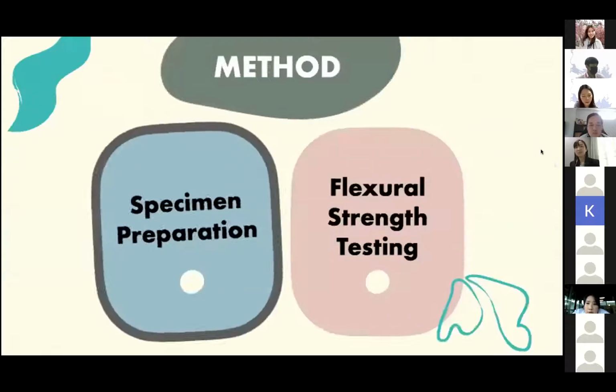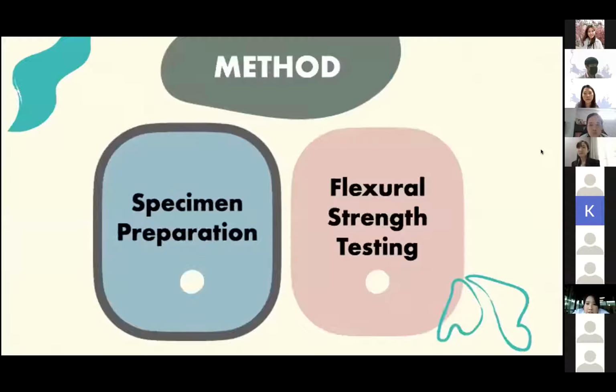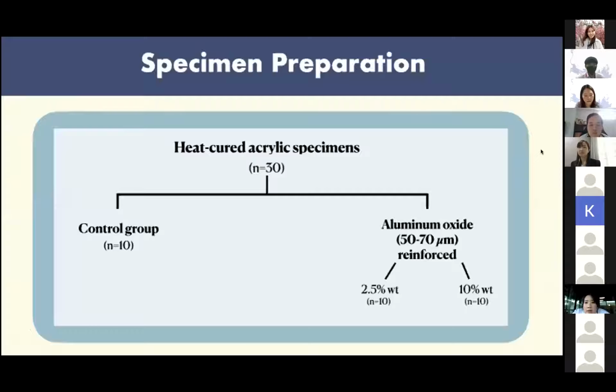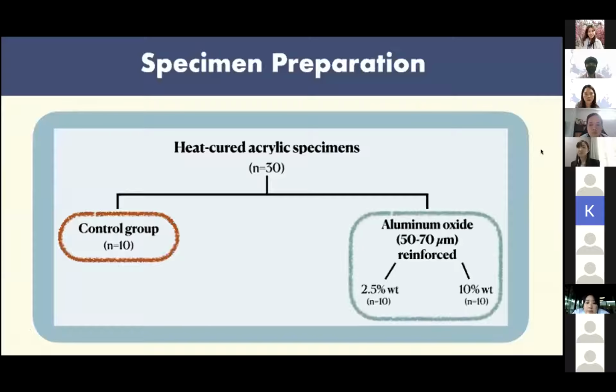Materials and methods. The materials used are as shown. Starting with the specimen preparation. 30 heat-cured acrylic specimens were fabricated. All specimens were divided into 3 groups. 10 specimens were the control group, which was intact heat-polymerized specimens, 10 specimens were the 2.5% by weight aluminum oxide reinforced group, and 10 specimens were the 10% by weight aluminum oxide reinforced group.